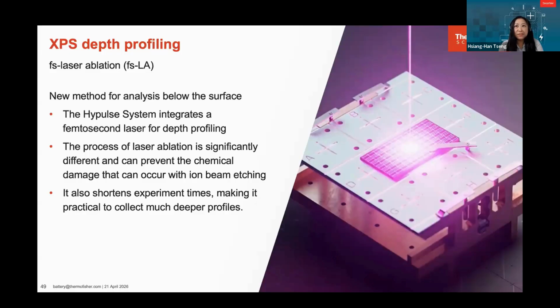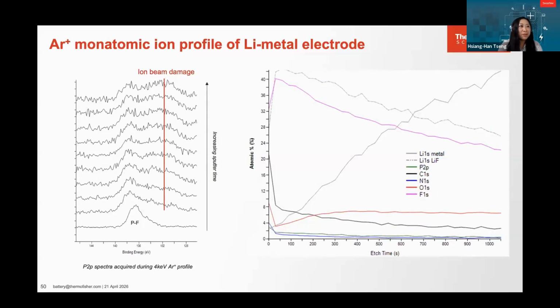And it actually has the advantage of not introducing chemical changes to the samples. But at the same time, because it's femtosecond, it makes the whole experiment times much shorter and possible and easier to collect a whole lot of series of profiles. But probably more exciting for us is that recently we've seen that this approach is quite suitable for looking at battery materials. So in the next few slides, I'll show you an example before we conclude.